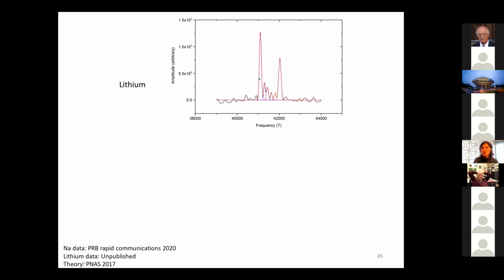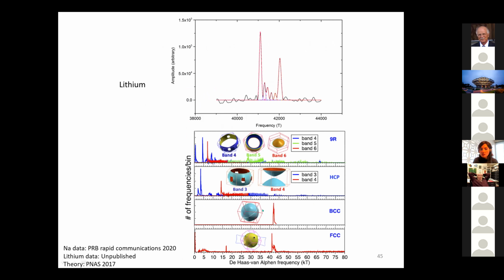So we compared it to the theory, and here we are collaborating very closely with theory, and we see, okay, we see some kind of a splitting in FCC. 9R distinctly doesn't have anything in this area, this martensite, and that was another indication that this 9R not only is not the ground state, but probably is not 9R altogether. Instead, the presence of these two peaks gave us an idea that maybe we are looking at something that is a combination of two other structures, BCC plus something else, maybe something close to FCC.